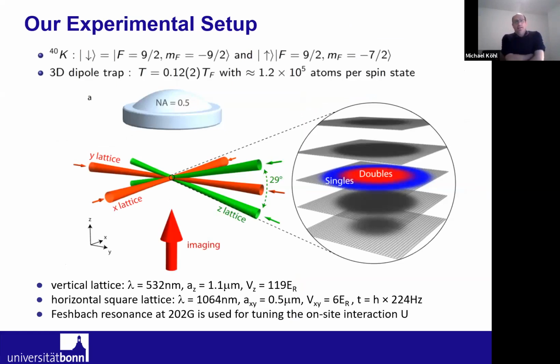So the experiment that we conduct is a relatively standard cold atom experiment. So we work with the isotope potassium-40. We take the two lowest hyperfine states of potassium-40, and we call these the spin up and spin down states. So this is our two-level system of fermions that we place into the lattice. We cool the gas down by standard methods, and then we arrange it in an optical lattice, which is constructed out of these 6 laser beams. The 2 green beams that you see here form a stack of 2-dimensional layers, as you can see here, where we confine the atoms to a very thin sheet where they move precisely 2-dimensionally. And then we superimpose these 2 pairs of red beams in order to form lattices in these planes.